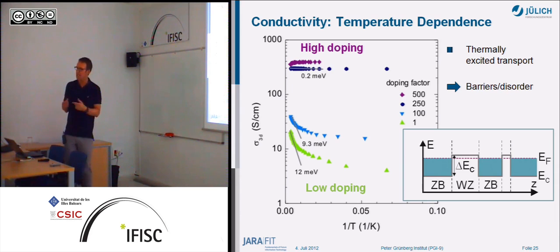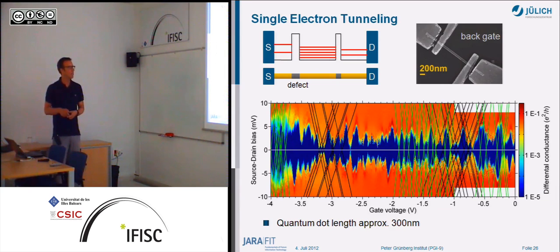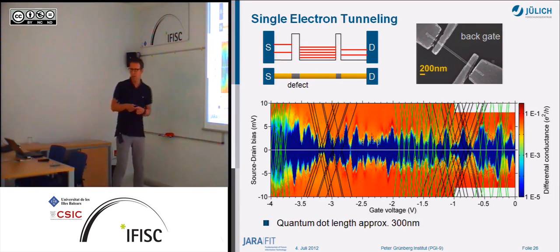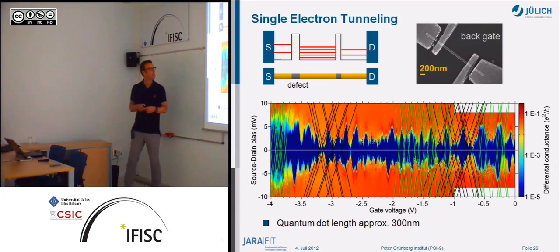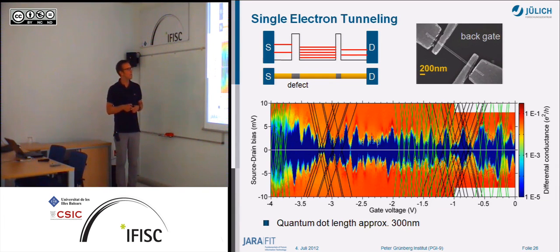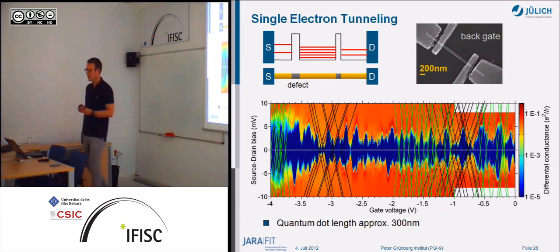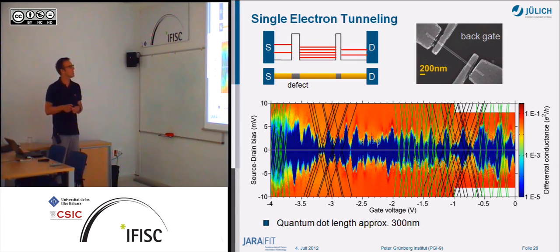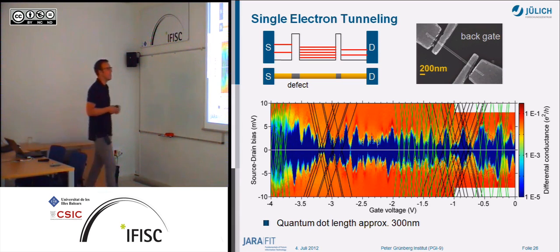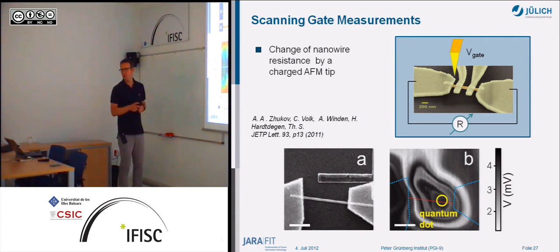Often they're not as ideal as you think at the beginning, that you have different crystal structures and that you have to take care of this. Also what can happen is that you can have defects in the nanowire. So if you measure the nanowires carefully at low temperatures, you see these Coulomb diamonds here, so you have single electron tunneling. Yeah, so what we think is that if you get the transport here, that you have defects in the nanowires which form some barriers, and then if you measure the transport, you see these characteristic Coulomb diamonds, which is an indication that you form some quantum dots here.